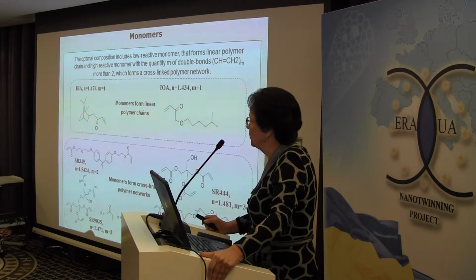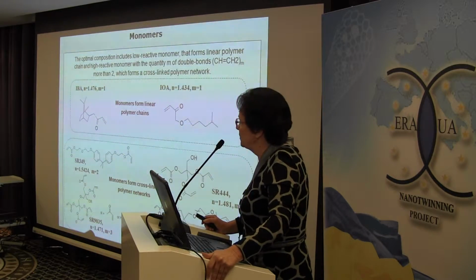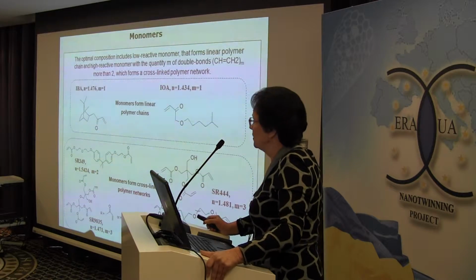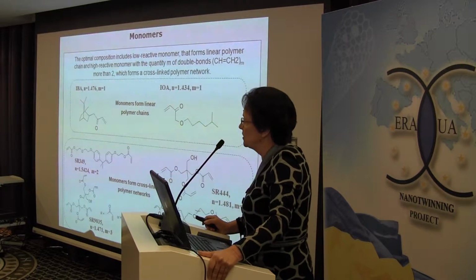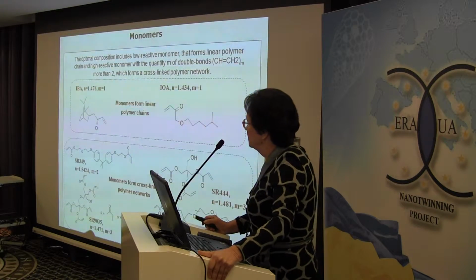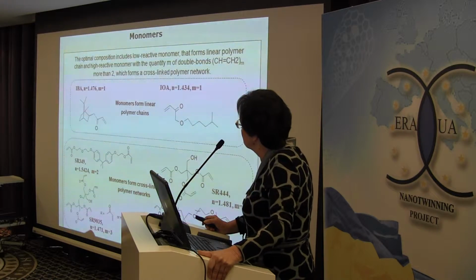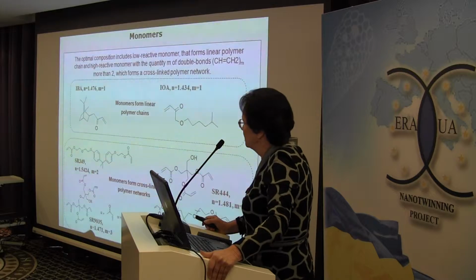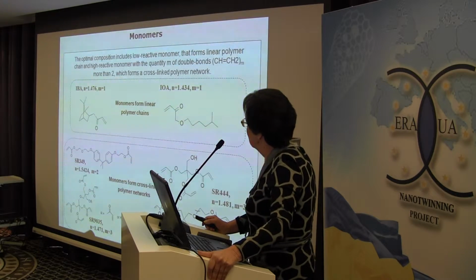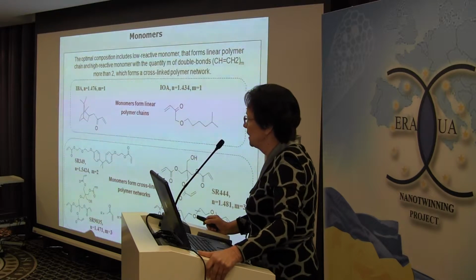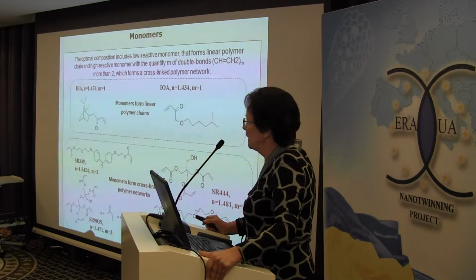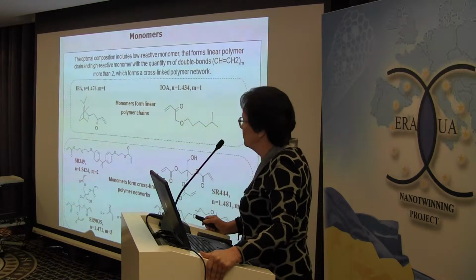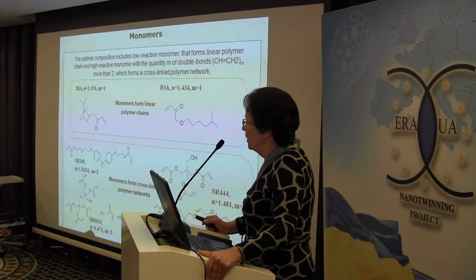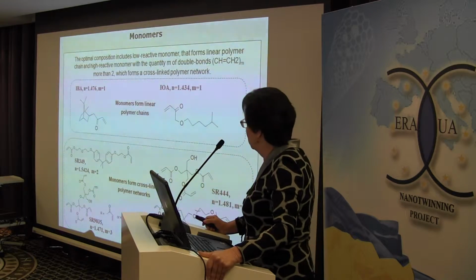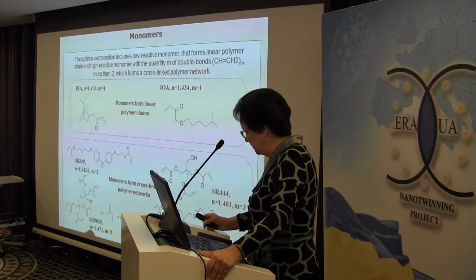The selection of monomer composition can be summarized as follows. The optimal composition includes a low reactive monomer with one double bond that forms the linear polymer chain, and a multifunctional high reactive monomer with a quantity of double bonds more than 2 that forms the cross-linked polymer network.